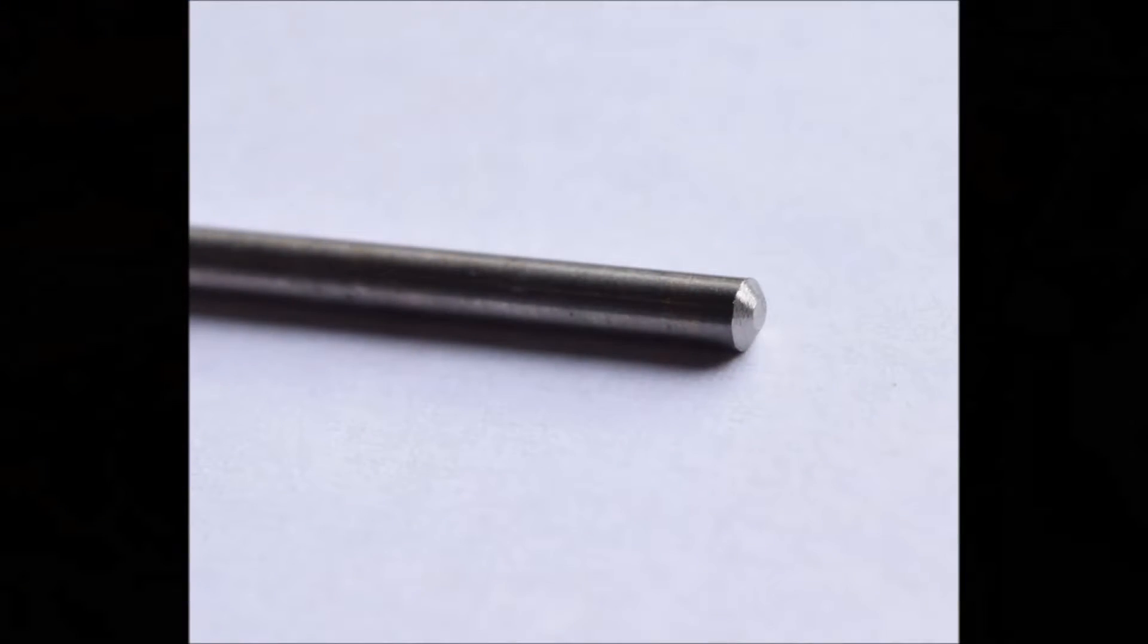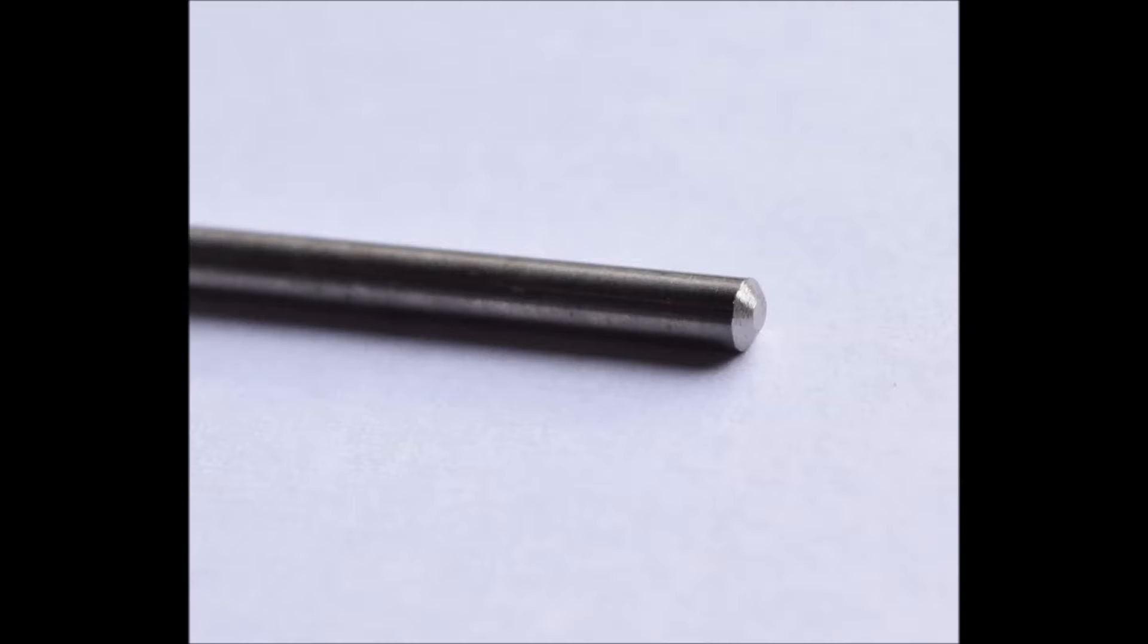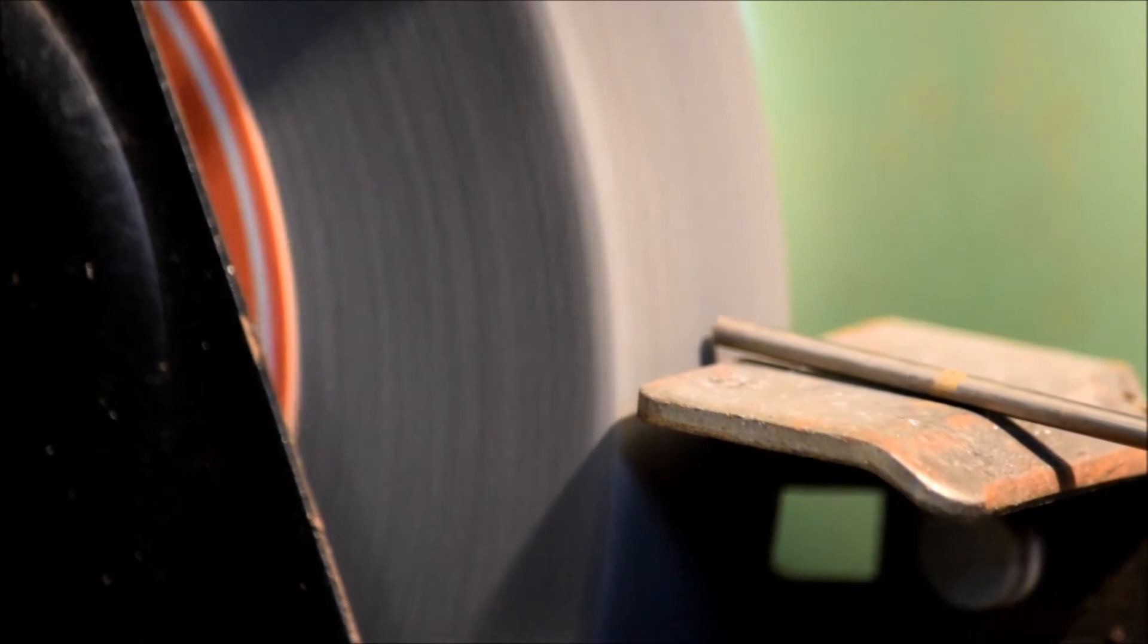Now we look at the preparation for welding aluminium. A sharp point is not permitted when welding aluminium because the arc is too concentrated for the low melting temperature of aluminium.